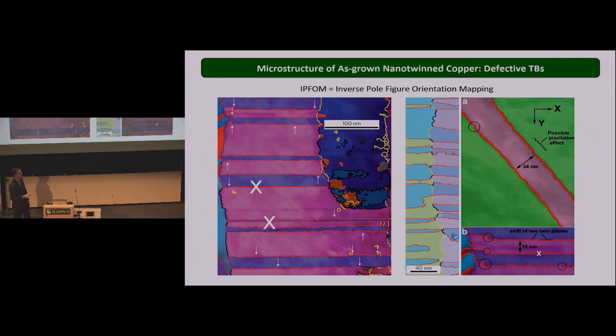If you had a conventional transmission electron microscope, you would see those grain boundaries with perfectly flat features, okay? Now in this picture, each pixel is a single diffraction experiment. It includes about 250,000 of these in this picture. And at the time, it took about 7 days to obtain that one picture, all right?